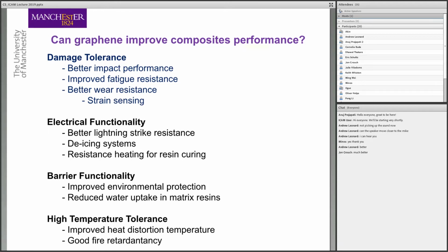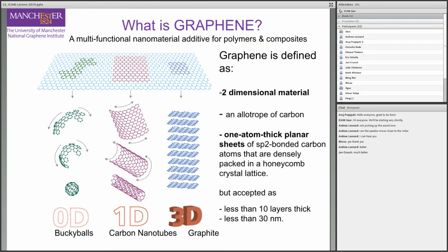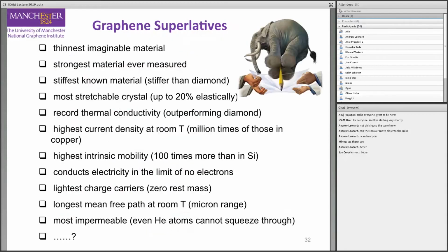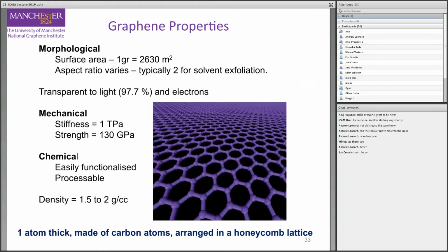But before doing that, let's see what is graphene. It's a multifunctional nanomaterial additive for polymers and composites. It's a two-dimensional material, one atom thick, with some superb properties. We claim that it's the thinnest, the strongest, the stiffest, the most stretchable. There's a long list of good things that graphene can offer us. And if we look at the stiffness, it's 1 terapascal with a strength of 130 gigapascals.